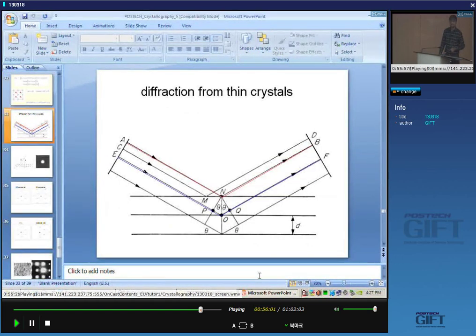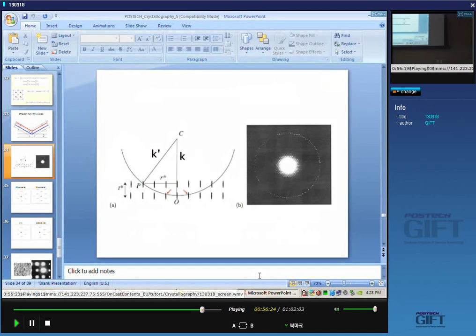Now, I pointed out to you that the Bragg law applies to crystals which are infinitely thick if you only want diffraction at the angle theta. As soon as you start making the crystal thinner, you will get diffraction even though you are not at exactly the Bragg condition. So when we use thin foils in a transmission electron microscope, that's obviously not an infinitely thick crystal. And even though the Ewald sphere doesn't intersect these spots exactly, you will get diffraction, okay?